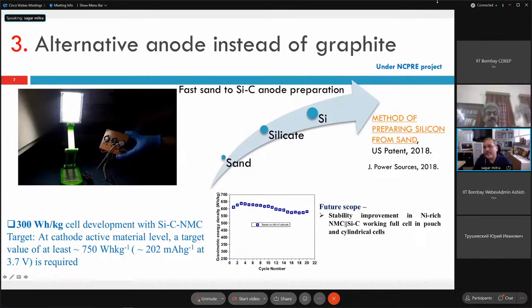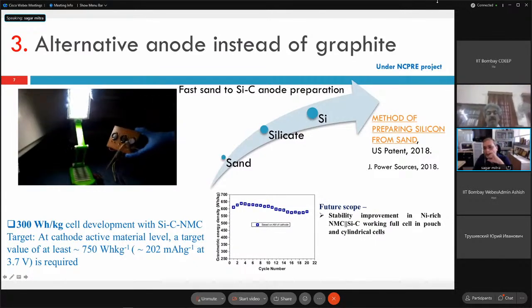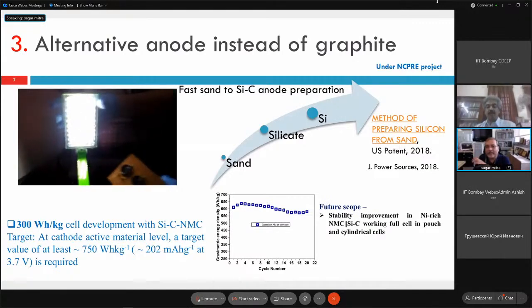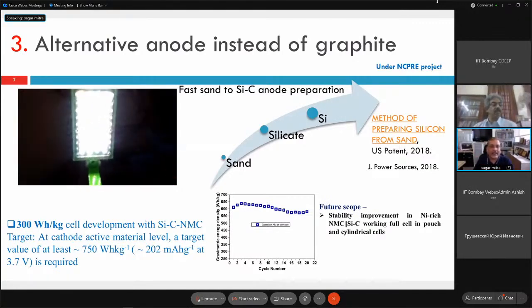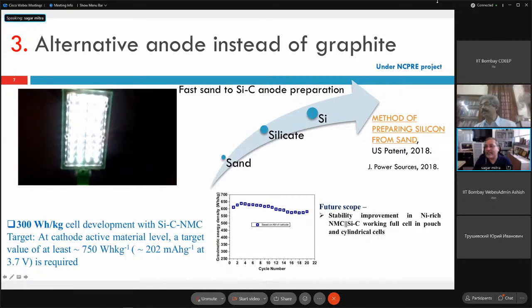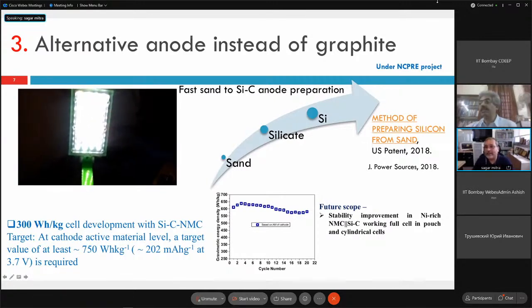Here we are making silicon from sand, and that is a very short-term process we have used. The target of our idea is that this silicon can be used on a larger scale. We have already done this for smaller time scales and smaller dimensions. You can see there is a demo going on, but we are trying to make the same composition of anode, compound it with NMC, and get it around 300 watt hour per kg. That's a target right now for electric vehicles. Even Tesla is trying to have 300 watt hour per kg.